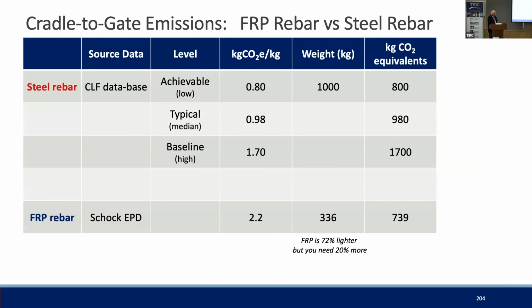So now let's do some math. What I'm comparing here is steel rebar versus FRP rebar. And for the steel rebar, this column contains the source data. I'm using the CLF database. And remember that there are 3 different levels given. Here are those values for kilograms of CO2 equivalent per kilogram. To keep the math simple, I've made it weigh 1,000 kilograms. And this column is simply the product of these 2 columns.